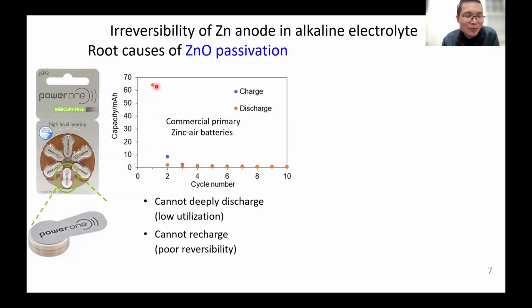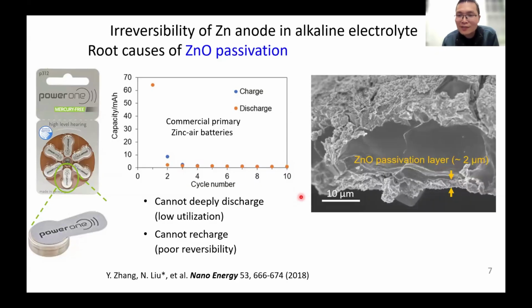But the problem is it's a primary battery, so you can discharge a lot of capacity, but you can't put the charge back. And in later cycling, you get virtually zero capacity. We analyzed this problem, and we think the first root cause for this is the zinc oxide passivation.